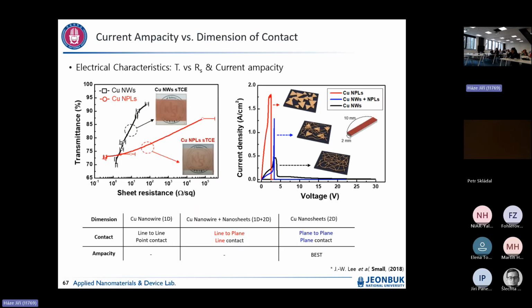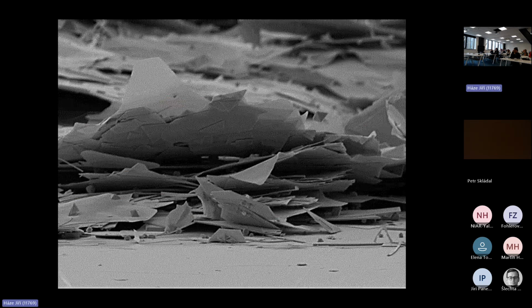And I'm going to skip this one. Then we tested a lot on how efficiently current flows in 2 dimensions. You can see here, this is the result from nanowire, and from mixing nanowire and nanosheet, and only nanosheet. It shows line-to-line results in point contact. Line is line contact. And finally, when you use the copper nanosheet, it shows really nice plane contact. It allows more control compared to the nanoparticle system or nanowire system. This is the real image. It really looks like A4 paper.